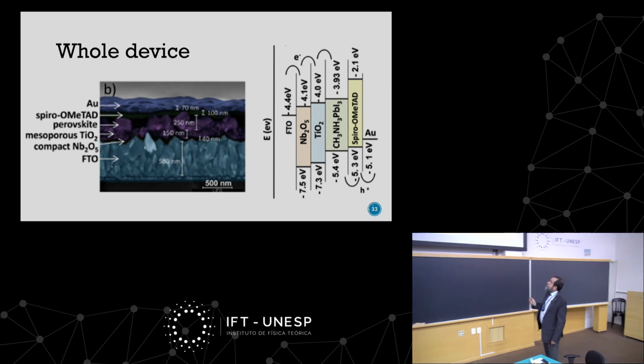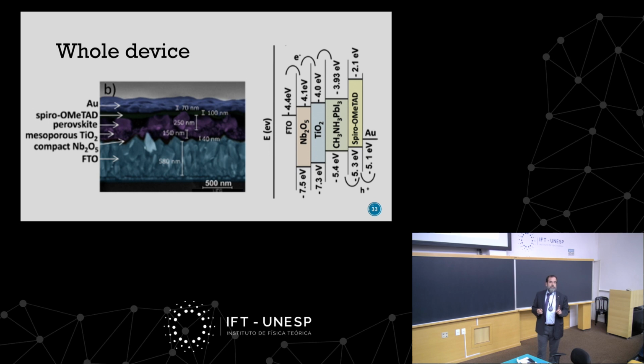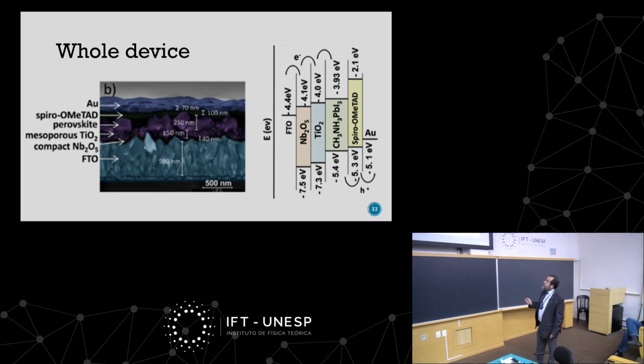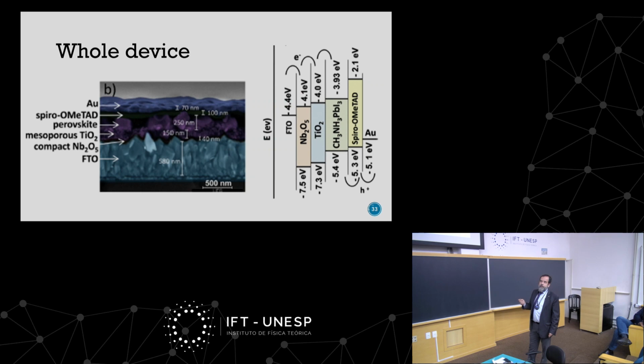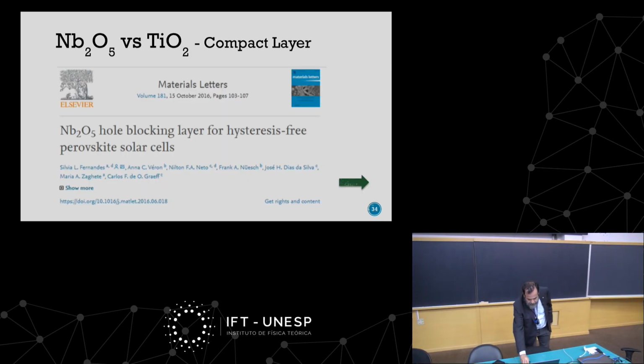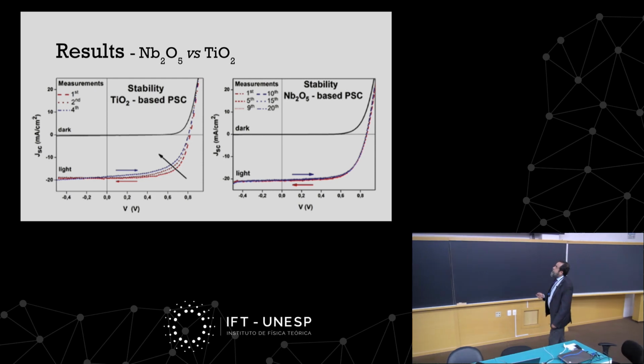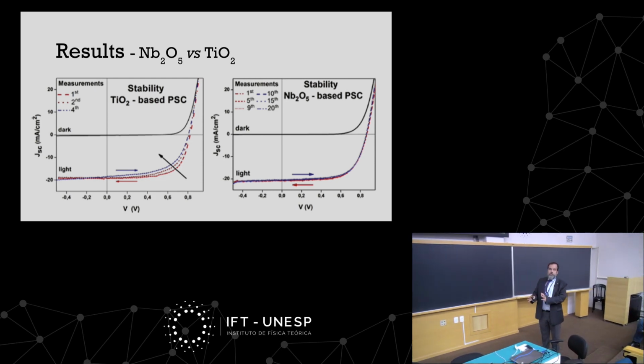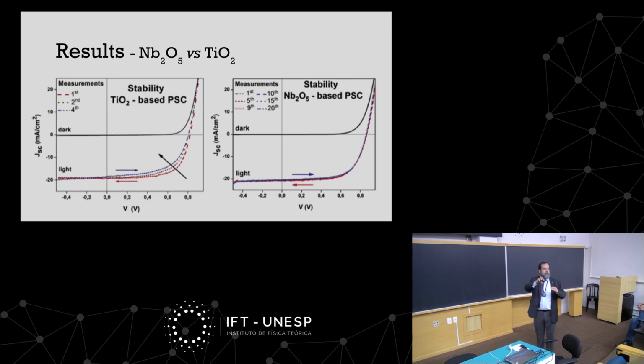Now I can talk a little bit about one big advantage of niobium oxide that will be more clear in the next slides. As you can see, niobium oxide is quite similar to titanium oxide, but it's not really equal, especially in what is called the conduction band. It's a little bit less in energy than TiO2, and this will be fundamental for what I'm going to explain next. So we made cells with the conventional technique, which is TiO2 compact, TiO2 mesoporous, and cells where the compact layer was changed to niobium oxide.